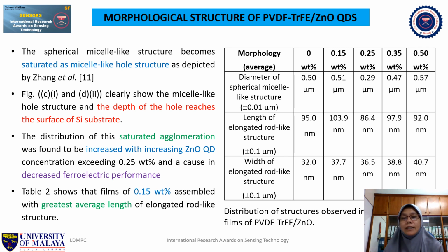This table in this slide shows the growth of the spherical micelle-like structure and also the elongated rod-like structure. So the length of elongated rod-like structure increases from 0 weight% up to 0.15%, and then reduces as the weight percentage of zinc oxide increases. So the diameter of spherical micelle increases at 0.15, reduces and increases again after the zinc oxide weight percentage is increased.